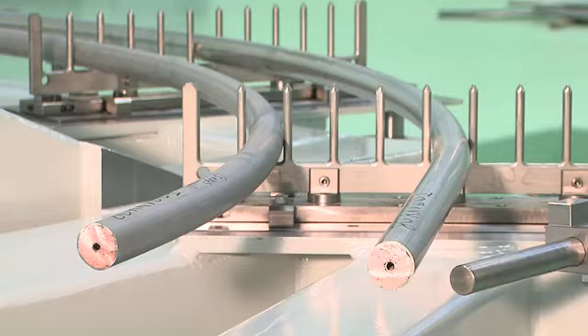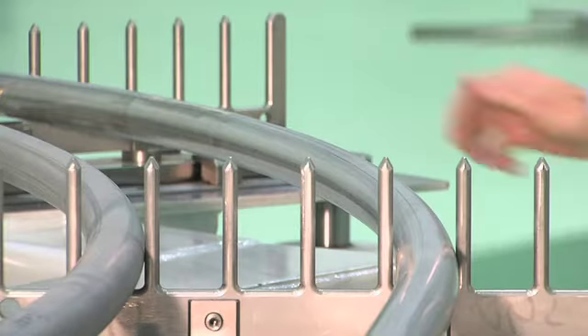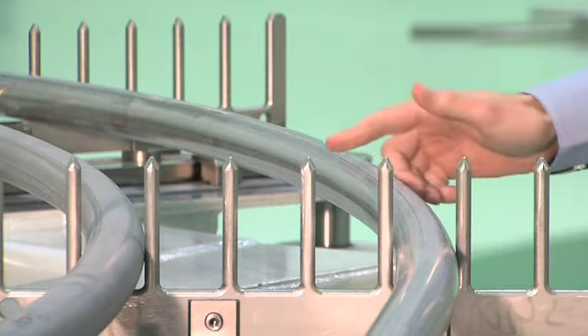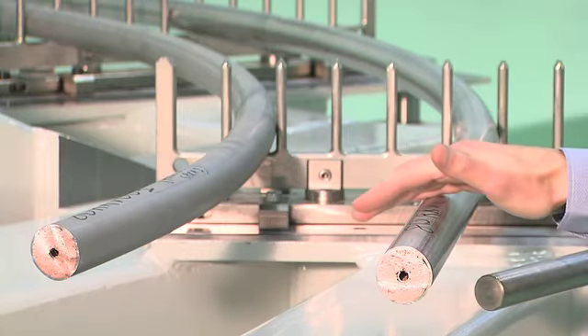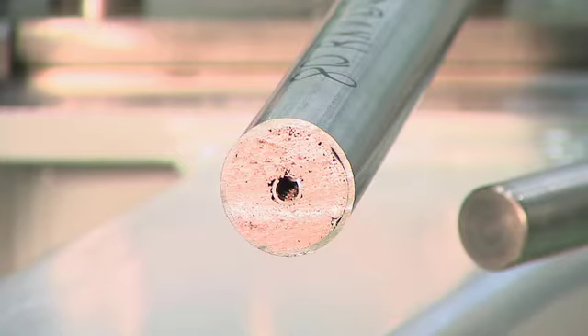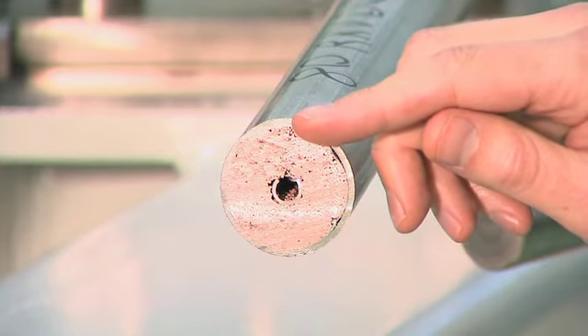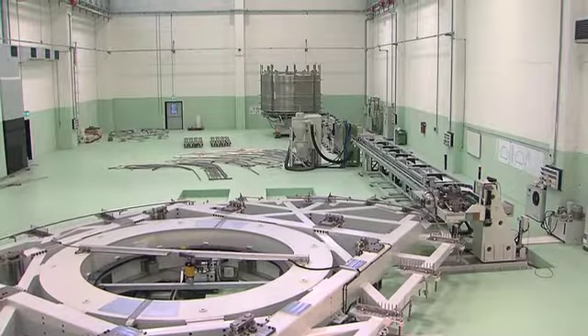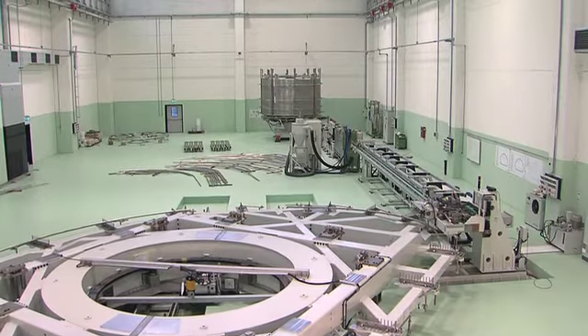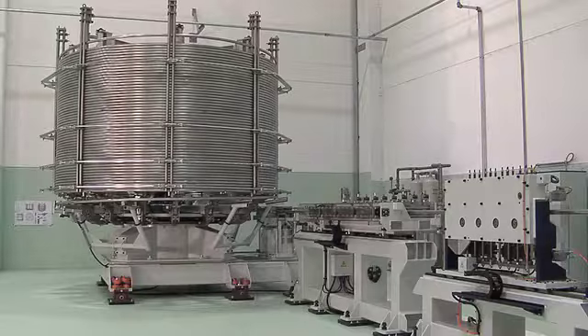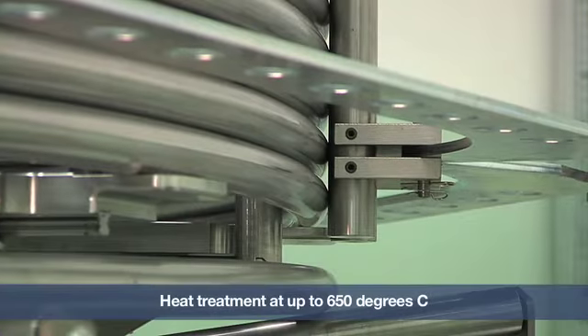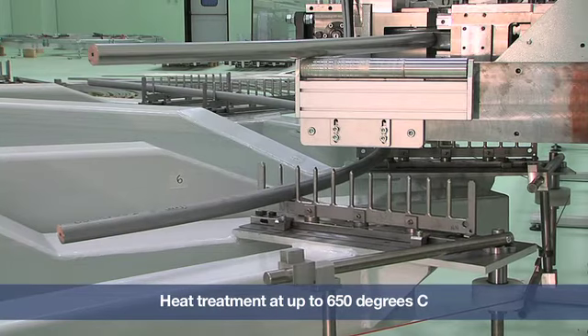The conductor itself is what is known as cable and conduit. It's formed from a cable of roughly 1400 niobium tin and copper strands, which are fitted inside a stainless steel conduit of about 45 millimeters diameter. An important aspect is that the superconducting properties of the niobium tin strands are obtained only after heat treatment at up to 650 degrees centigrade.